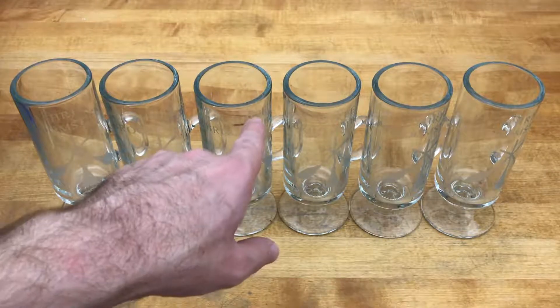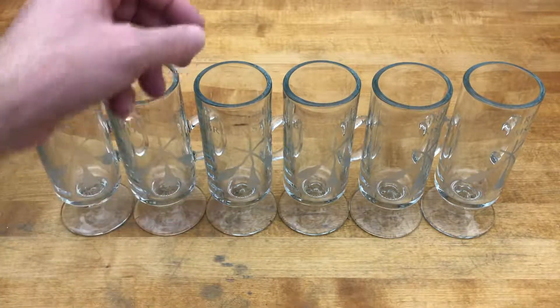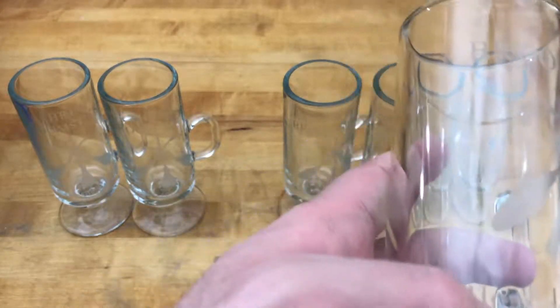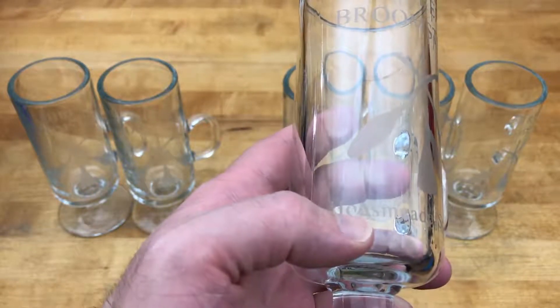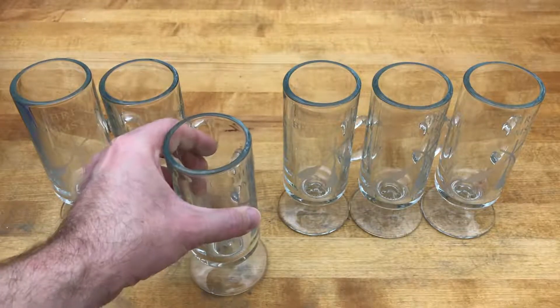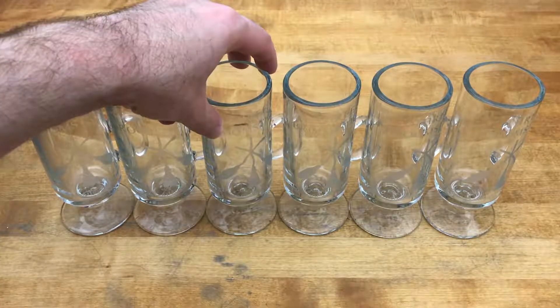I think if I were going to do another project like this I'd probably try to find something other than the vinyl to use as a mask, especially if I'm going to do this many. The vinyl — weeding it took me an hour, then getting all the little pieces out of all the letters was kind of a pain as well. And I did have the problem where those narrow spots sometimes the etchant didn't get in there. So next time I might look for something other than the adhesive vinyl to use as the resist.